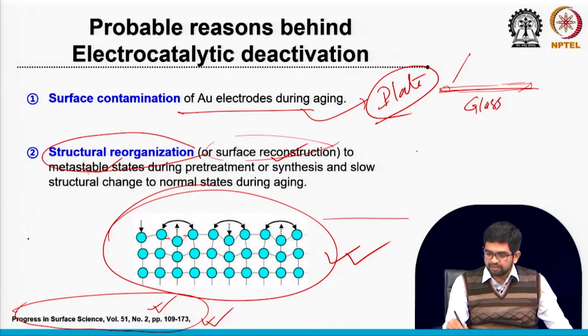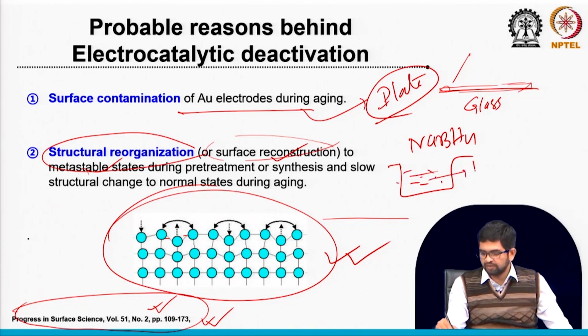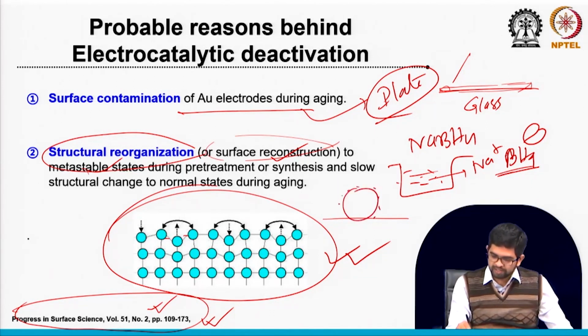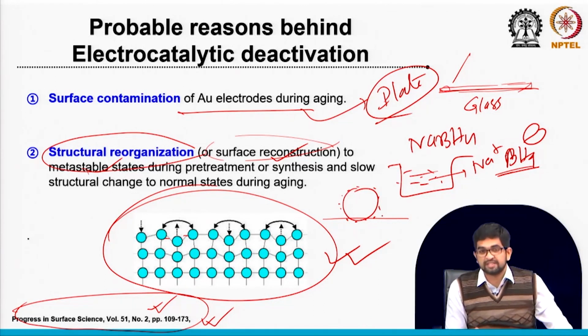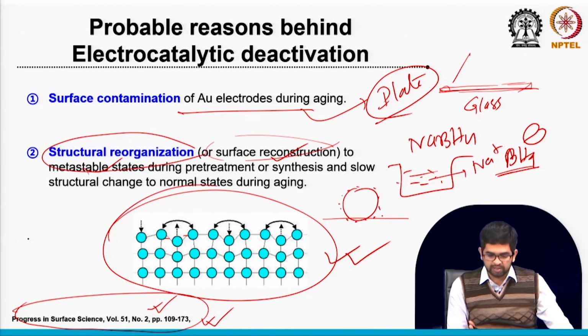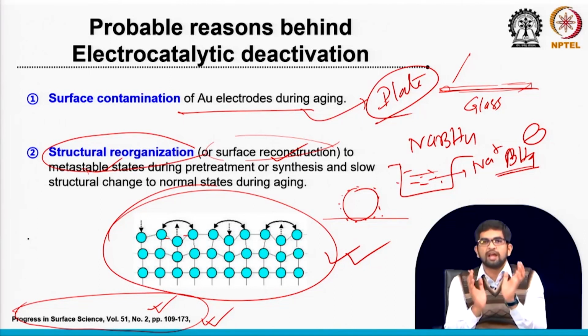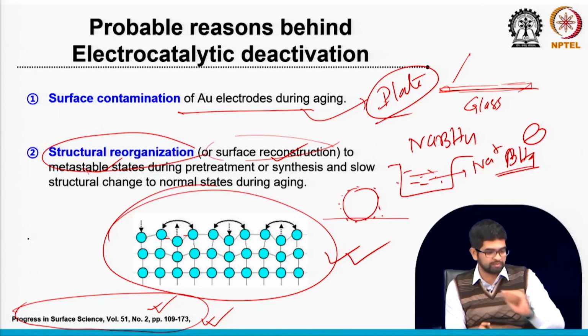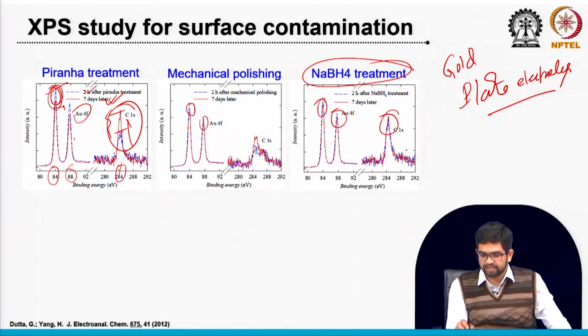This is because when we carry out the sodium borohydride treatment in a solution, you know Na+ and BH4- are forming, and I think I taught you already that from this borohydride, the hydrogen atom can adsorb on the surface, and this hydrogen atom can make some metastable state, some strained surface. Due to this, maybe we can improve this electrocatalytic activation. So from this sodium borohydride treatment, you can see the gold peak shows not much change after 7 days, but still we can see the activity change. Carbon also shows not much change after 7 days.